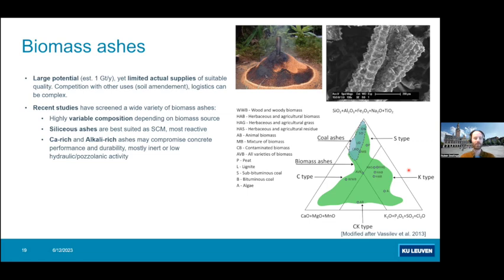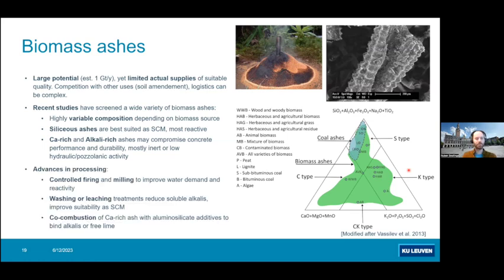Compatibility is also sometimes an issue. They're not very reactive and may disturb the reactions of the cement, so one needs to be careful. And wood ashes, for instance, are typically calcium-rich, sometimes even also potassium-rich. However, people have tried to resolve some of these issues.